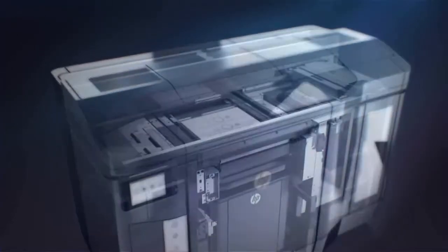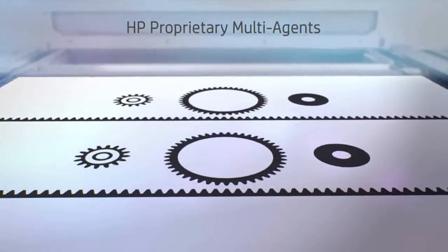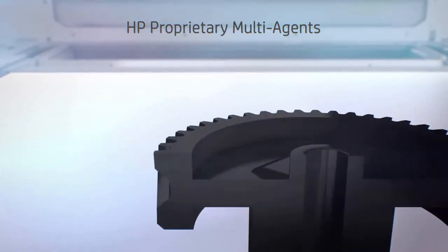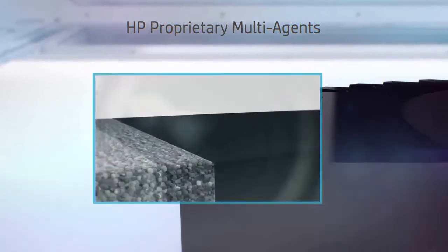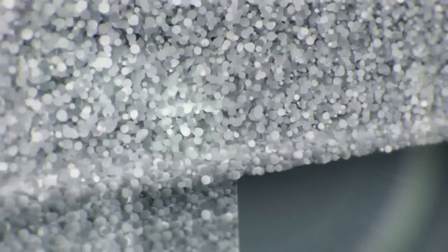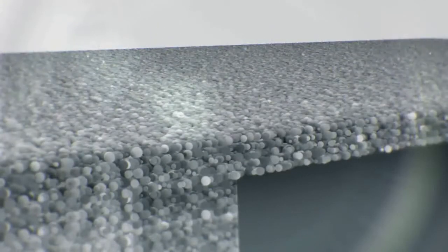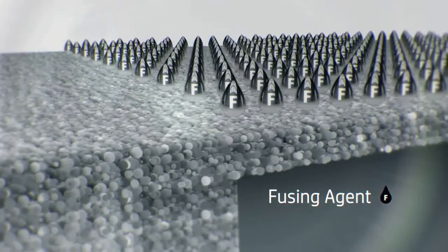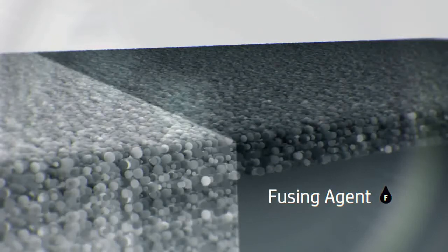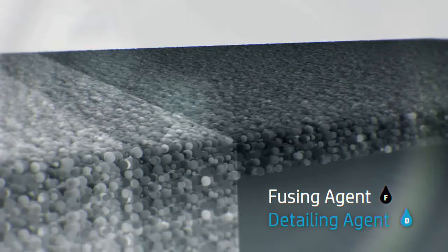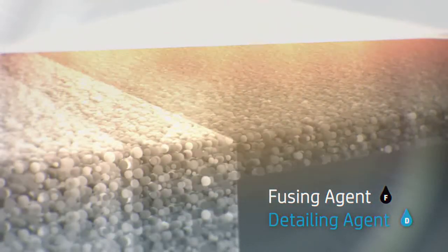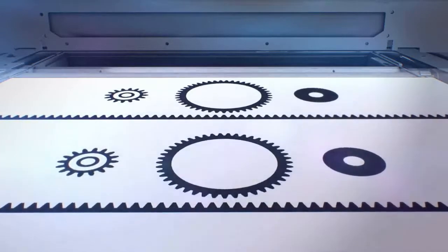To produce truly functional parts, it's important to ensure that the material has been properly fused and that part edges are smooth and well-defined. To achieve part quality at speed, HP invented a multi-agent printing process. In this process, a fusing agent is applied on a material layer where the particles are meant to fuse together. A detailing agent is applied to modify fusing and create fine detail and smooth surfaces. The area is exposed to energy, and reactions between the agents and the material cause the material to selectively fuse together to form the part. The fusing process requires accurate temperature control across the entire material layer.